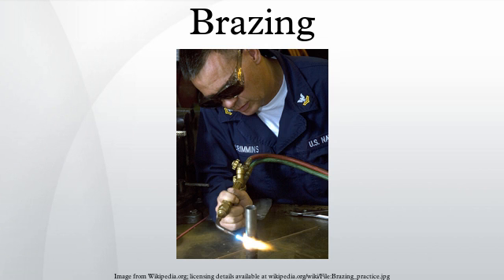The three main types of vacuum furnace are single-wall hot retort, double-walled hot retort, and cold-wall retort. Typical vacuum levels for brazing range from pressures of 1.3 to 0.13 pascals to 0.00013 pascals or lower. Vacuum furnaces are most commonly batch type, and they are suited to medium and high production volumes. Silver brazing, sometimes known as silver soldering or hard soldering, is brazing using a silver alloy-based filler.